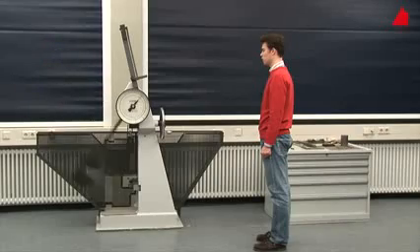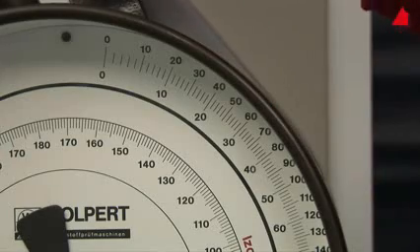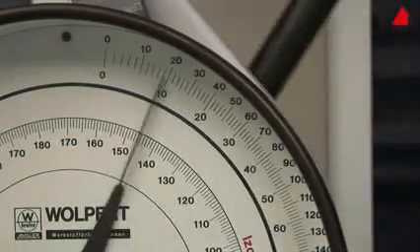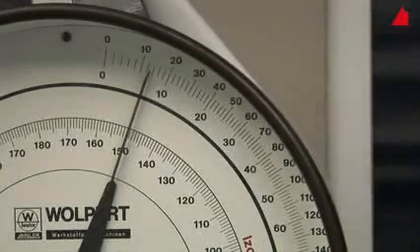The amount of energy that has been absorbed by the specimen can now be read off at the position of the drag indicator. It only amounts to 13 joules in this test.